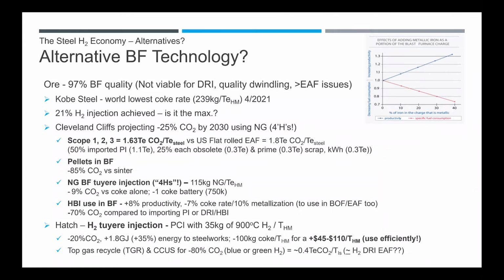In the US, Cleveland Cliffs, they've used natural gas, basically saying, hey, that's got 4 hydrogens, and they are predicting that they can reduce their CO2 by 25% by 2030, stating that their scope 1, 2, 3 are basically lower than those of the electric furnace flat roll products in the US, being 1.63 versus 1.8 tons of CO2 per ton of steel. But that's mainly because they're expecting 50% use of imported pig iron, and they've associated 1.1 tons of CO2 to that particular import. They're looking at pellets in the blast furnace, which reduce the CO2 85% versus sinter.